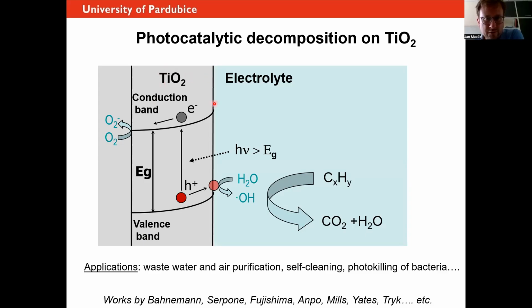So you have a TiO2 surface, and you have a surrounding area like atmosphere, but it can be also a solution, for instance. And what happens here is that when you have a UV light coming on the surface, there is excitation of the electrons from the valence band to the conduction band. And so this is really semiconductor physics, and there are some things that happen here. So there are some positively charged holes that have tendency to travel to the surface. And then they actually react with the water.